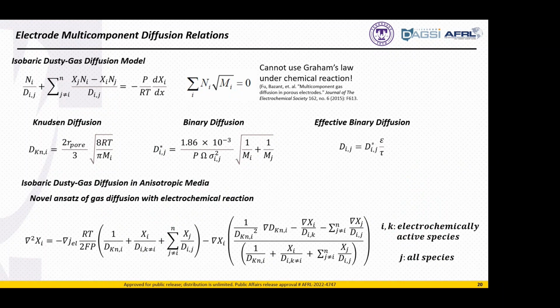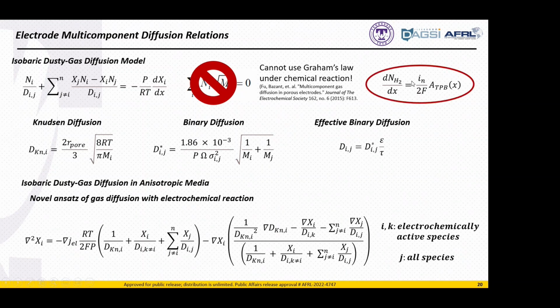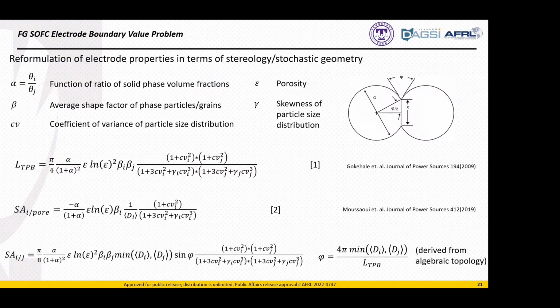Another thing that we did, just correcting from literature, is some folks had used a dusty gas diffusion model, but, excuse me, they had used Graham's law to decouple the dusty gas diffusion model, but this isn't appropriate under chemical reaction. And instead, we related this to the molar flux, which is going to result from the exchange current density of the electrode, and then came out to this novel expression here, which is somewhat cumbersome, but can be numerically integrated and is going to account for this anisotropic media, where my composition or my porosity is going to change throughout the depth of the electrode.